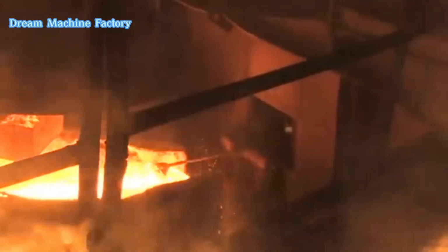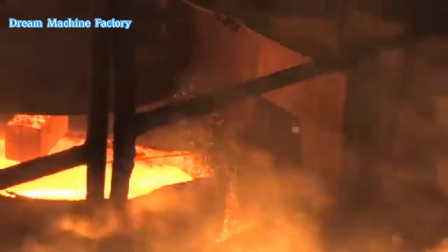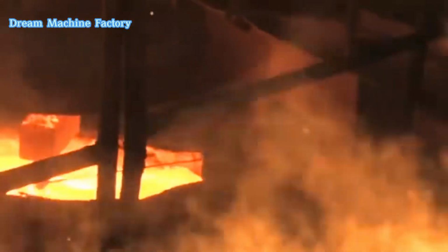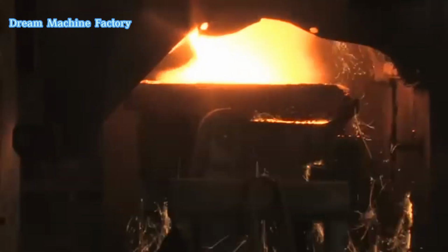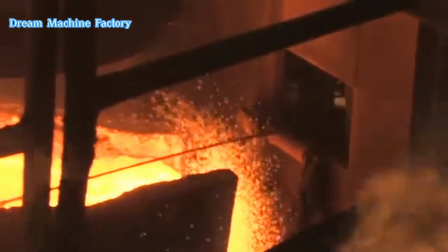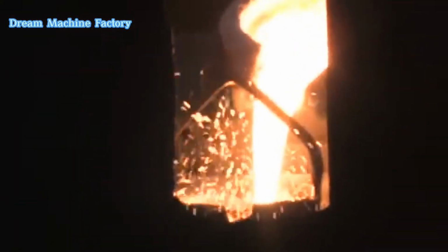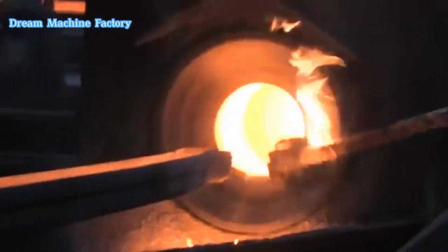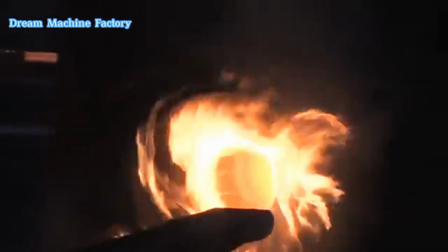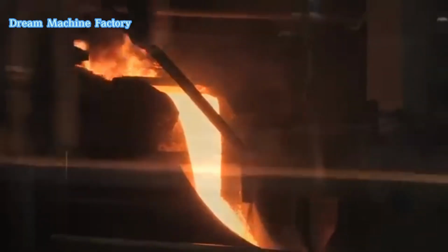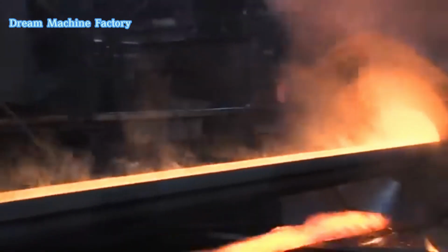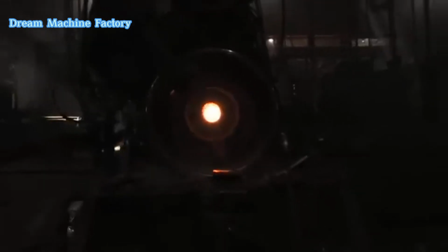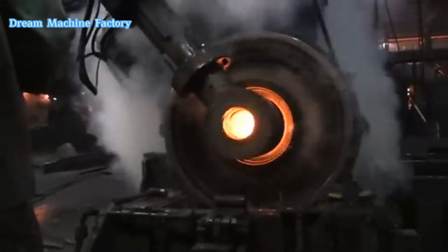Silicon is also introduced to enhance the metallurgical properties of the iron. As the metal melts, it flows out of the tap hole into runners that direct it into ladles. At this stage, the molten iron undergoes desulfurization, where calcium carbide is added to reduce the sulfur content. An operator skims off slag and spent carbide to ensure the molten iron is clean. Samples are taken for metallurgical analysis to verify the composition and quality of the metal before proceeding to the next step.